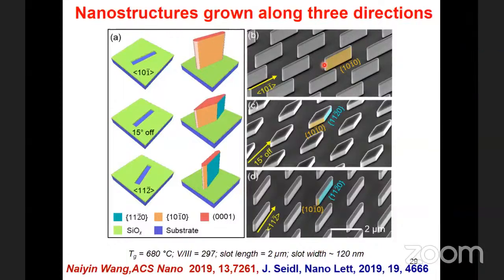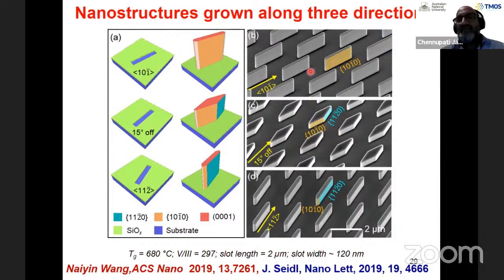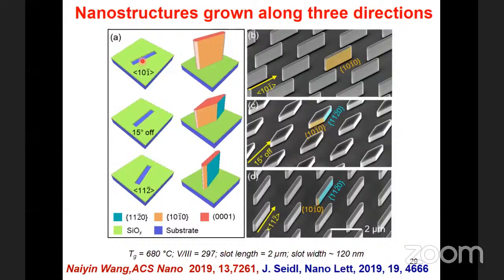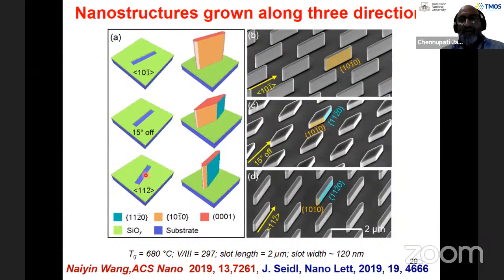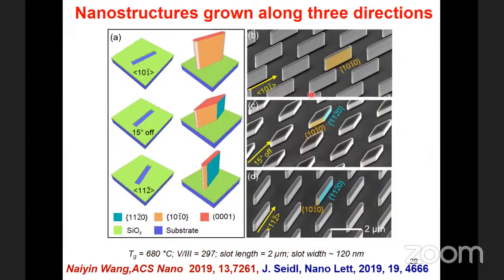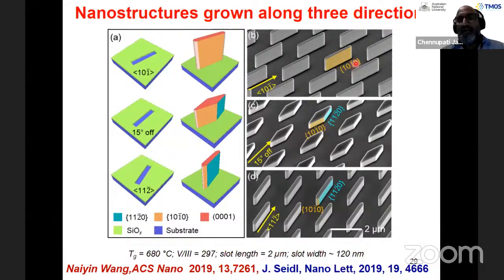And then you can see that you can get beautiful membranes in this case with this particular facet, sidewall facets here. But if you open the slot on another crystallographic orientation, 112 bar here, again you can get membranes, but in this case the facet is different because of the changes in the crystallographic orientation. And then if you open the slot in between these two crystallographic orientations, you can get these beautiful diamond-like structures with these alternating facets of these 101 bar 0 and then 112 bar 0.